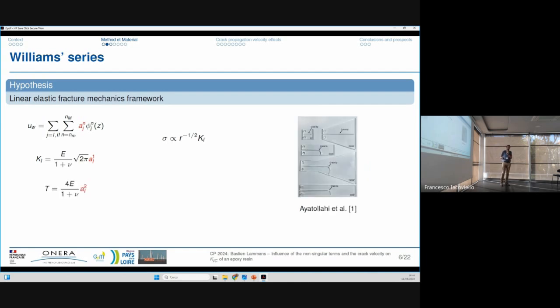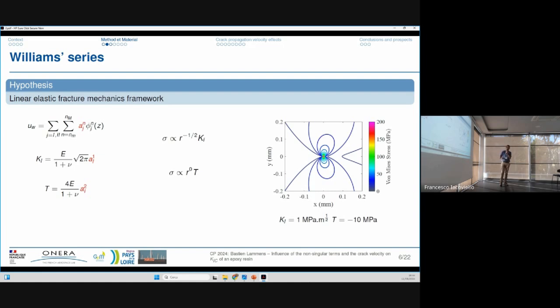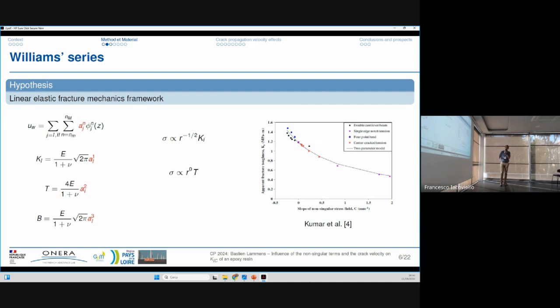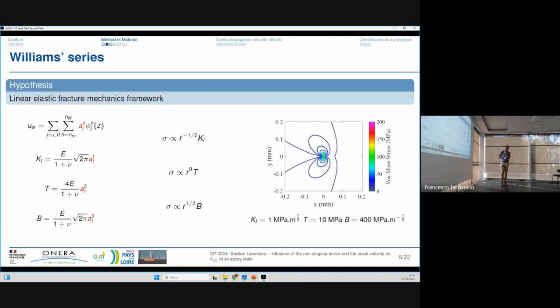But the literature shows that there are also non-singular terms that have to be taken into account to see geometrical effects. Ayatollahi mentions that there are different crack paths according to the considered specimen. If you look at the influence of the T-stress value, you can see that if you change the value of the T-stress, you have a modification of the far stress field. Kumar studies the B-stress, the second non-singular term, and shows an influence on the apparent fracture toughness that depends on the considered specimen. Now, if you look at the von Mises stress, you can see that the modification of the B-stress has an influence on the far stress field because it depends on the stress by this relation.